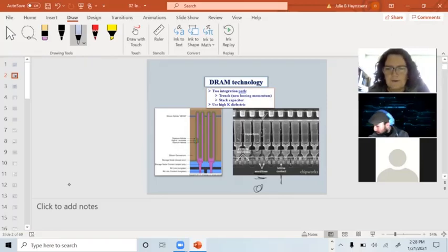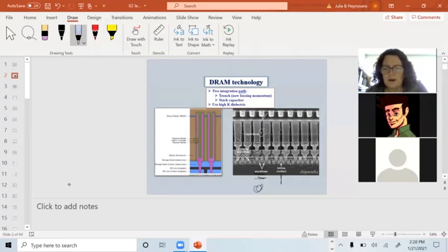So right here, notice that there is a little bump. This is a defect. It's not big enough to short between capacitors, but it doesn't take a lot of imagination to think that there's going to be places where those bumps are a little bit bigger, and I'm going to short out the capacitors. So burying the capacitors deep into the substrate like this, I have issues with shorting. Another thing too is there's a parasitic capacitor between the capacitors because they're running parallel for so long next to each other. There's crosstalk between adjacent cells.